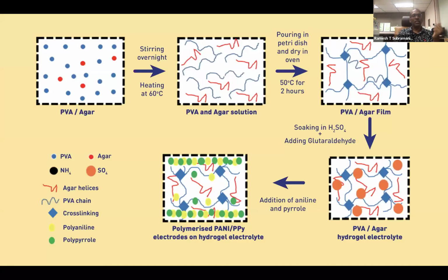For this all-in-one configuration, you can see here, for example, say we have a polymer like PVA and agar. First, we make them as a solution. Then we make them as a film. Once we make them as a film, then by using an appropriate initiator and cross-linking agent, we make them as a hydrogel. Once we make them as a hydrogel, next we grow the electrode on top of the electrolyte. This is done by addition of aniline and pyrrole, and they will polymerize, and the PANI and polypyrrole will cover the electrolyte on the surface.